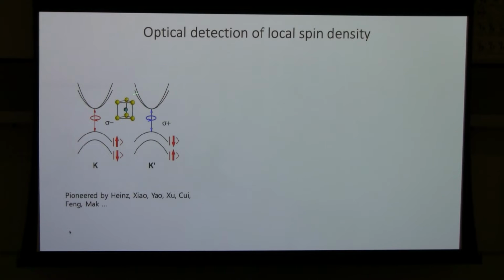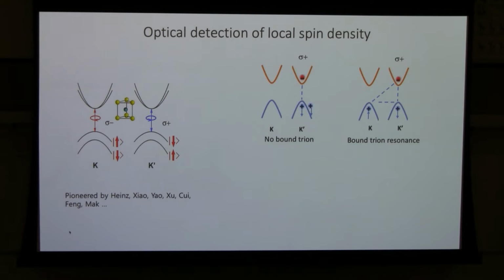With this information about optical selection rules and spin valley locking, we can now ask not what happens to the exciton transition, but what happens to the trion transition. Imagine we add a spin down hole in the system. Because of the spin valley locking, the spin down hole is at the K prime valley. In this case, if you use a circular polarization like sigma plus that measures excitons in the same valley, this excited exciton and the residual hole will have the same spin for these two holes. Due to Pauli blocking, when you have two holes with the same spin, they cannot form a bound trion state. So in this case, you will not see any trion resonance.